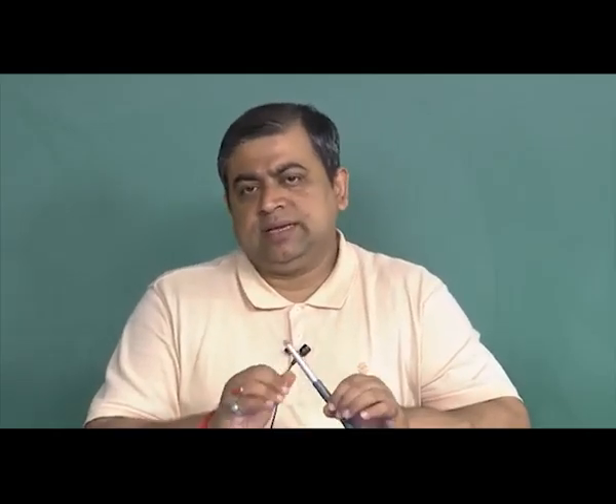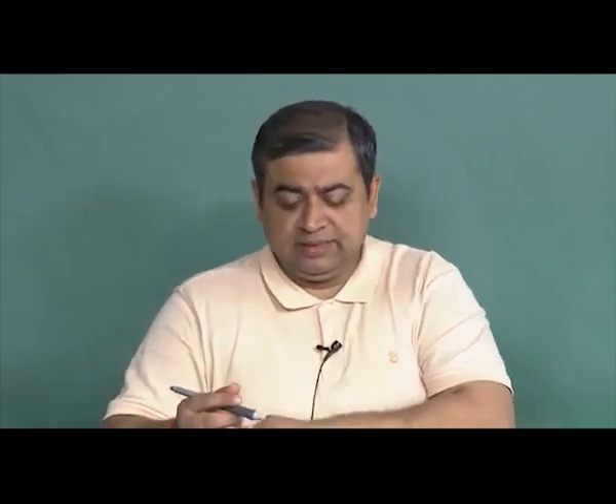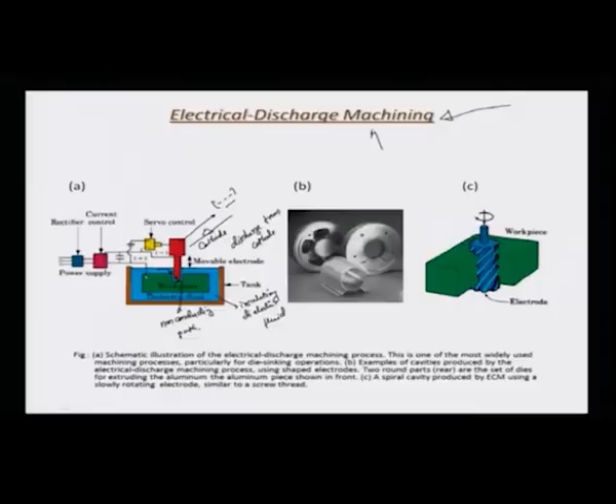And as the electron pressure reduces on the surface, there is a tendency of cavitation to happen, because the medium itself is not so fast as the electron velocity, and it has high inertia, and so it takes some time for the medium to come back into that portion. And so, for a momentary instant, there is a creation of a low pressure zone which creates the pull of the melt pool which has been formulated, and that is how you remove the material in this particular process. So, it is a useful tool, electro discharge machining, just like electrochemical machining.